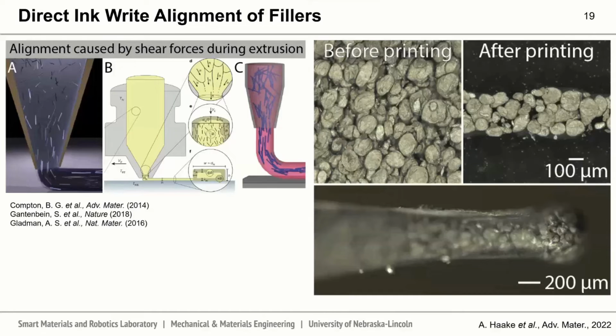If we print the elastomer composite as an emulsion, meaning liquid metal droplets within a prepolymer matrix, we see almost no visible change in the microstructure of the liquid metal droplets before and after printing. Even looking at a zoomed-in microscope image of the nozzle as the material is extruded, we see primarily spherical droplets throughout the length of the nozzle before and after extrusion.